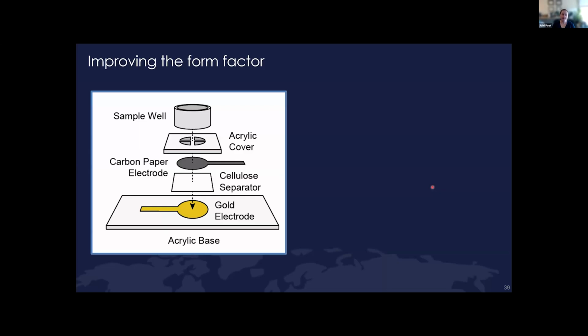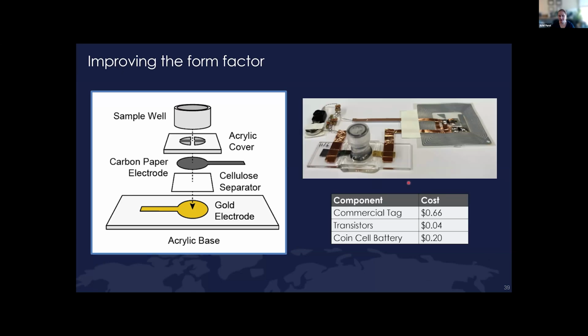And what this actually looks like is it's a pretty simple setup. We have those gold leaf electrodes that I described in the first story in the talk, separated by a cellulose separator from a carbon paper electrode. We can just 3D print this half of a cap and put a sample well on top of that. What it looks like in practice is this, where this is our sampling system and this is specifically our sample well. We have that connected to an RFID tag, which is also connected to an external switch and battery. And because these are all off-the-shelf components, it costs us less than $2 per device.